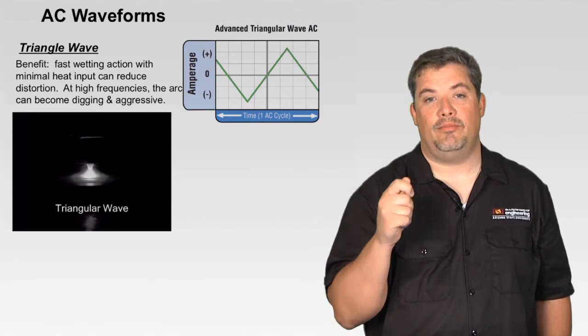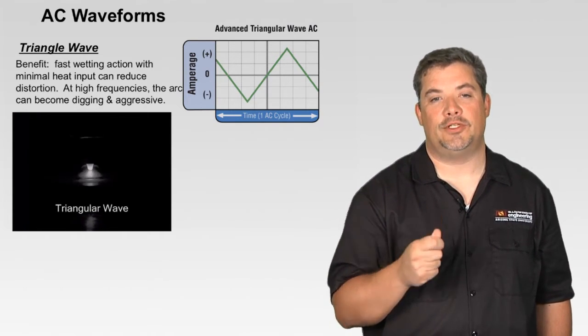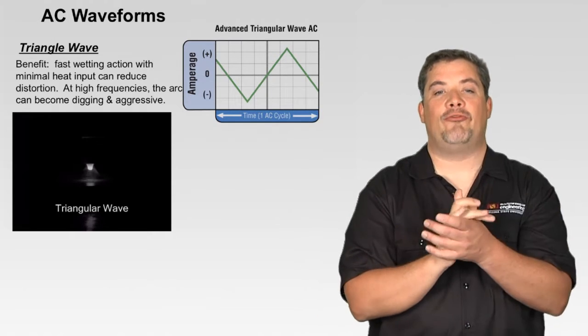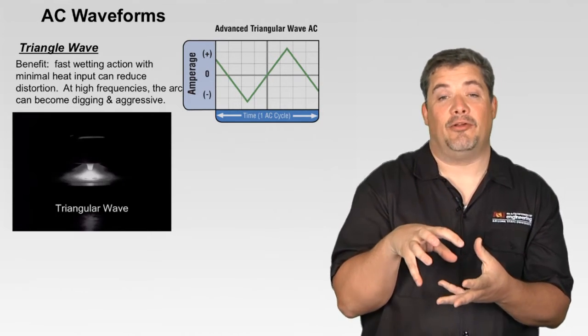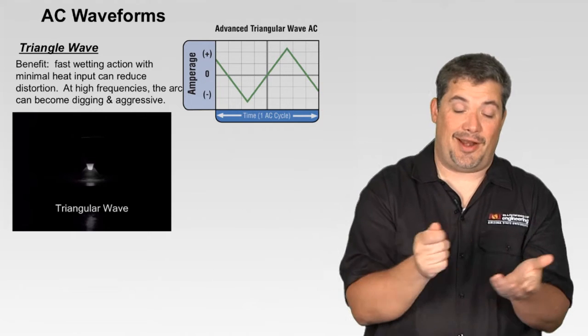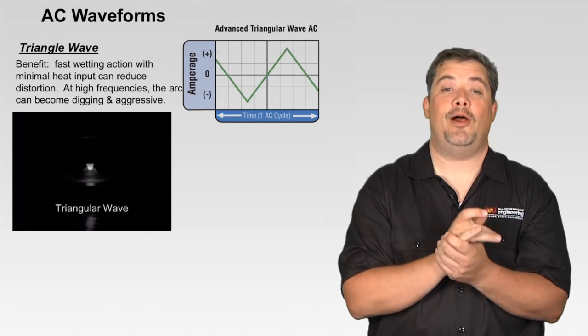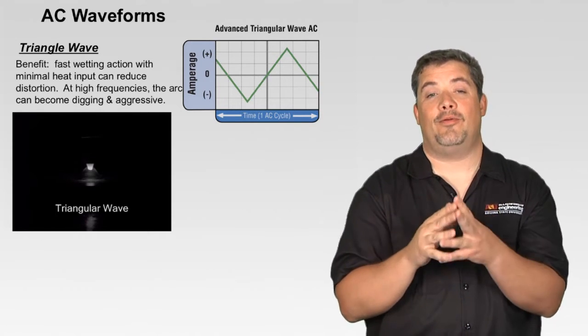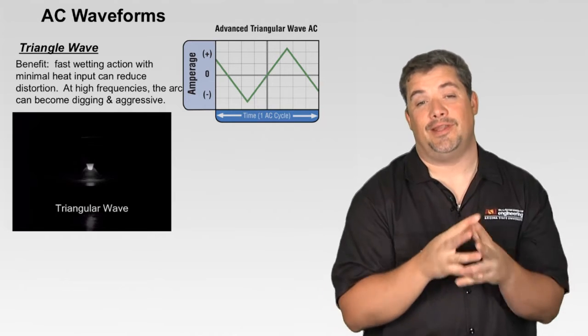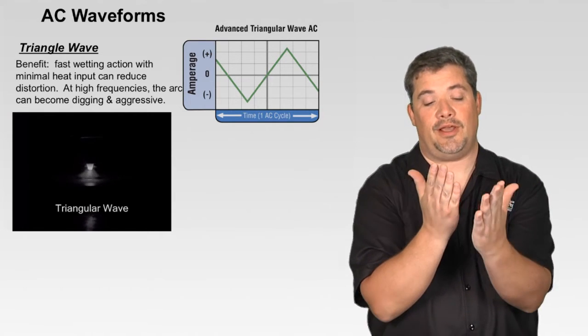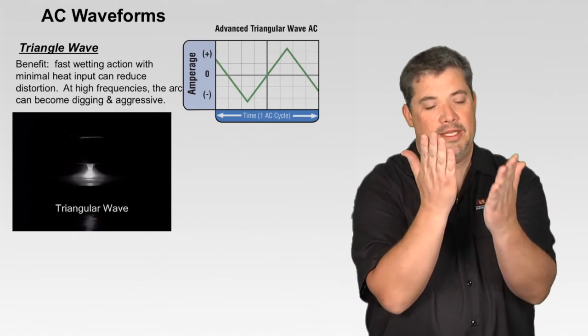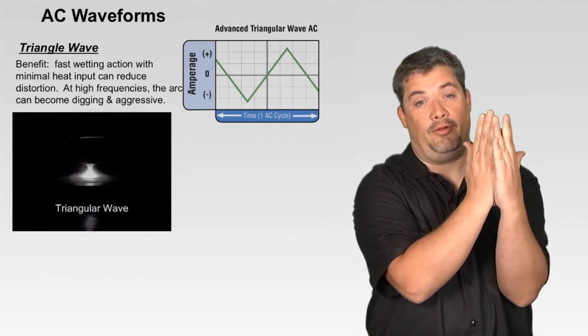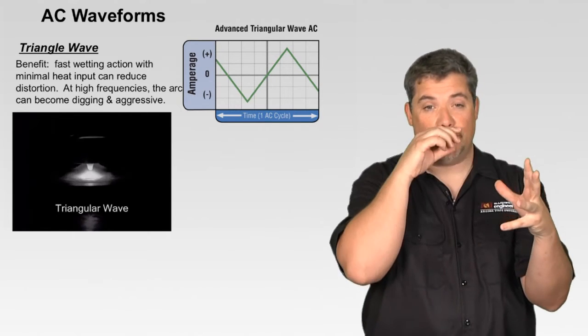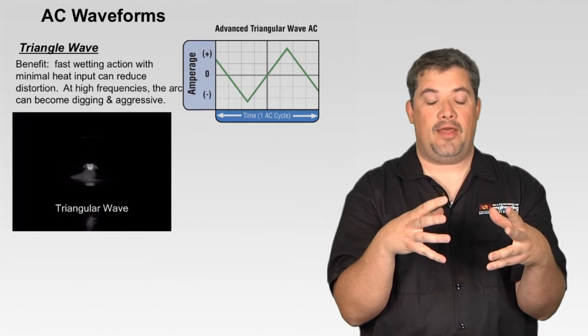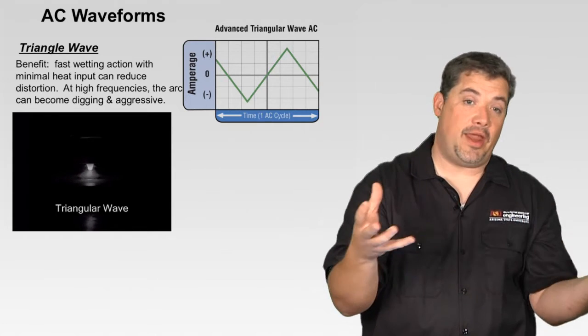Great wetting action, minimal heat input, and it can reduce distortion. At high frequencies, it can actually become very digging and aggressive. There's actually companies that use it to try to cut into a part before they weld it. Kind of crazy. But another place that it's awesome is in the aerospace industry. Aerospace welders have to do an extremely thin wall T-joint weld test in the vertical position. And they have these big fixtures that are heat sinks, and these heat sinks just take all that heat away.